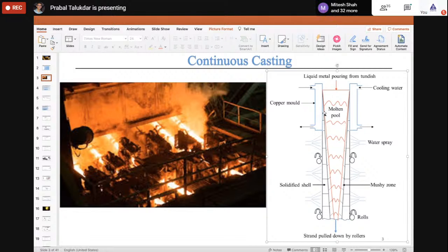This gap is not shown in this diagram, but I'll show you in some other diagram. Between the mold and the solidified shell, a small gap is produced, and air is trapped in that small gap, and because of that, the heat transfer rate reduces. You all know that air has a very low conductivity. When there is air between the solidified strand and the copper mold, the heat transfer reduces, and that affects solidification, right? Solidification doesn't happen properly. So the main idea is that the heat transfer rate should be as high as possible, and you should make your copper mold of such a shape that the gap doesn't happen.